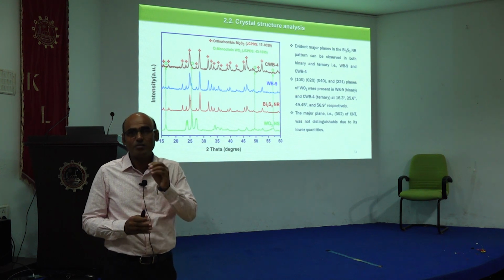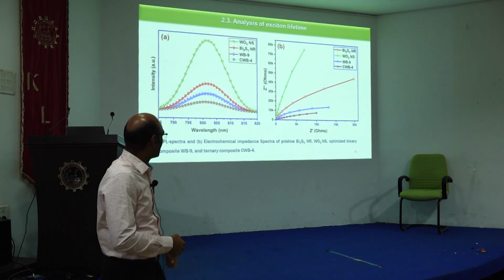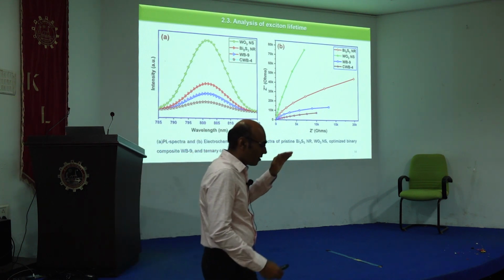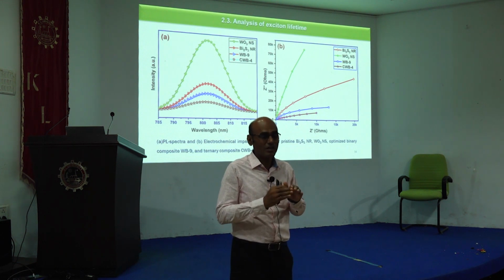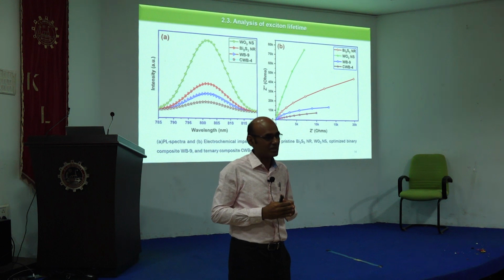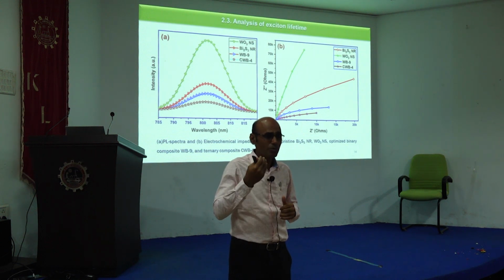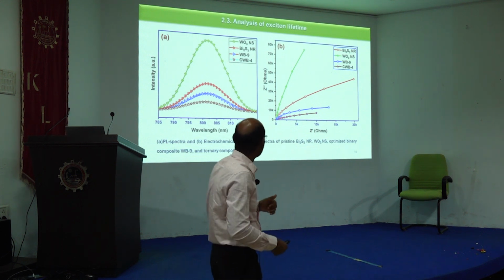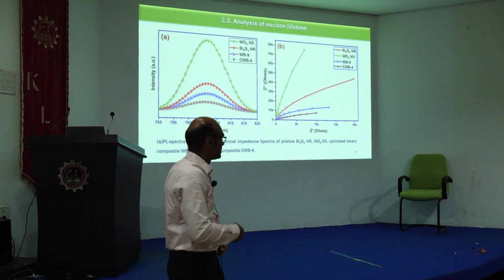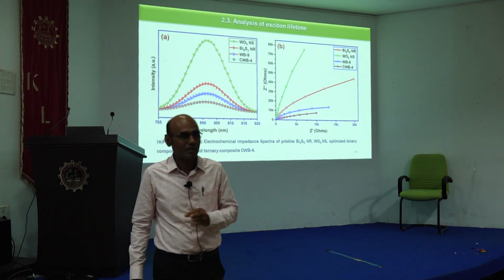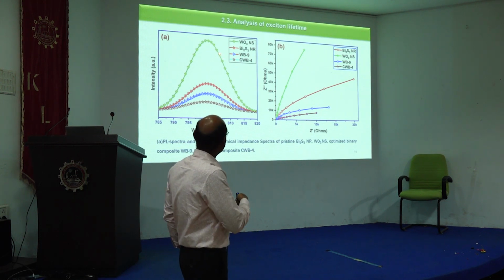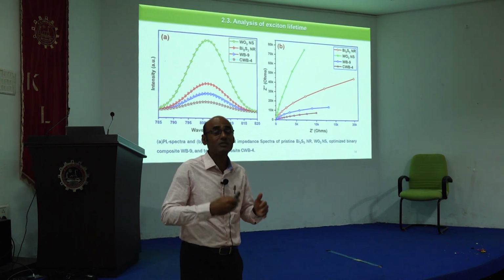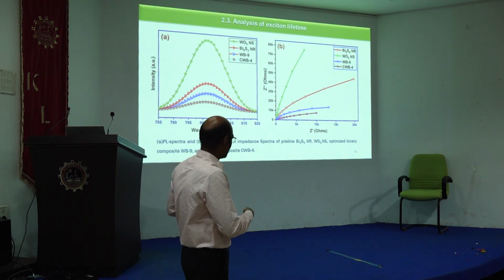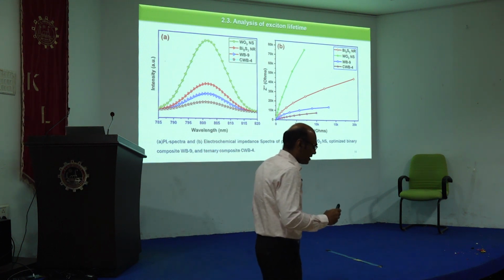So this is very preliminary information about the synthesized material, and now our interest is to suppress or minimize the charge carrier recombination. By that way it can be effectively used for the reaction. Whether my material has improved charge carrier behavior and suppressed recombination or not, we can check using a simple first-level technique, photoluminescence at a given wavelength, that is PL spectra. In the PL spectra, for the pristine material you can see the peak intensity is higher, and when the intensity is lower, that means the charge carrier lifetime is better and recombination is lower. So compared to the pristine material, the binary and the ternary materials have better charge carrier lifetime.